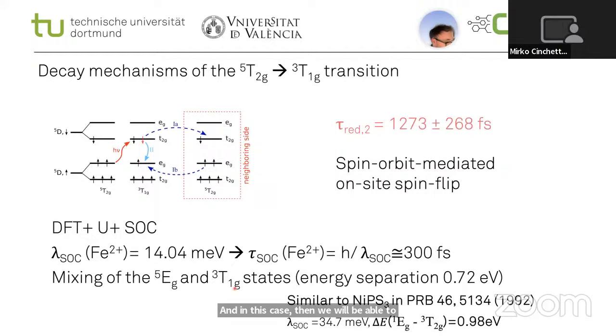Moreover, this spin-orbit constant also makes sense for interpreting the data like this, because in nickel PS3, a similar value of this spin-orbit constant was deemed to be sufficient to mix these 1Eg and 3T2g excited states, and this mixing then enables the spin forbidden DD transition. So basically we have the same interpretation for our data. The spin-orbit coupling would mix the 5EG and the 3T1G states, and in this case we will be able to get our spin flip on a time scale of the spin-orbit constant.